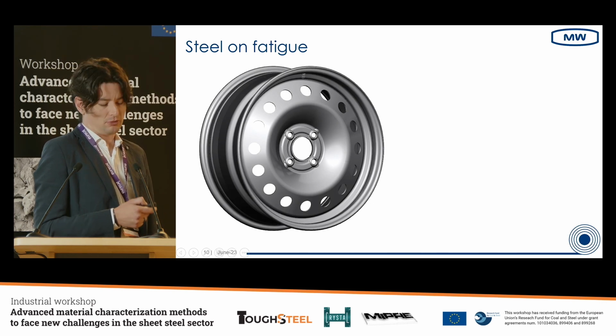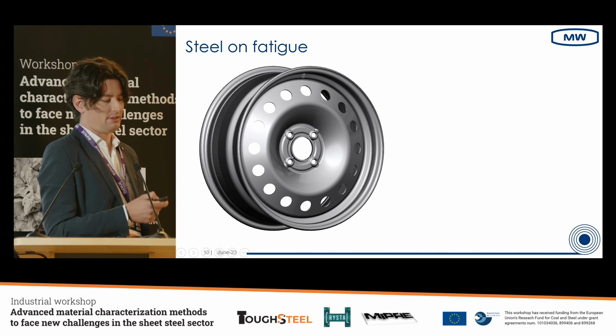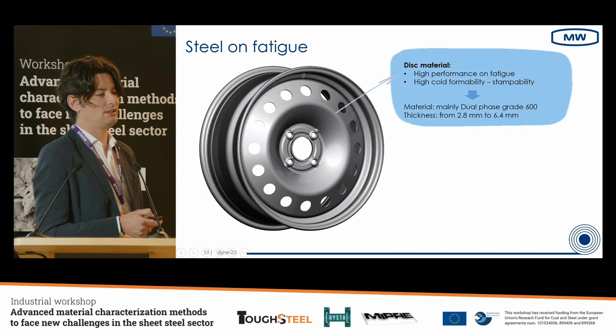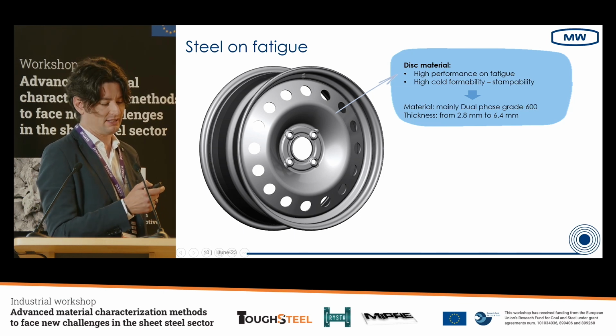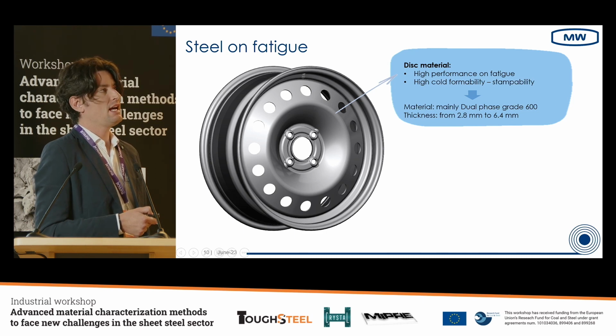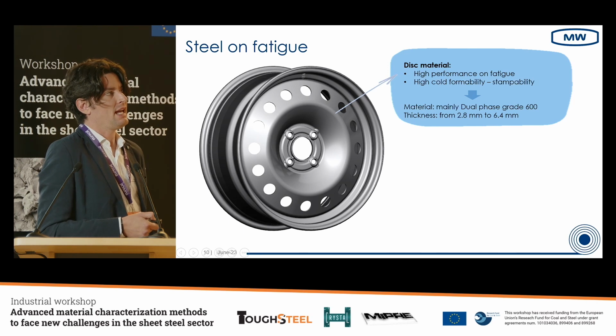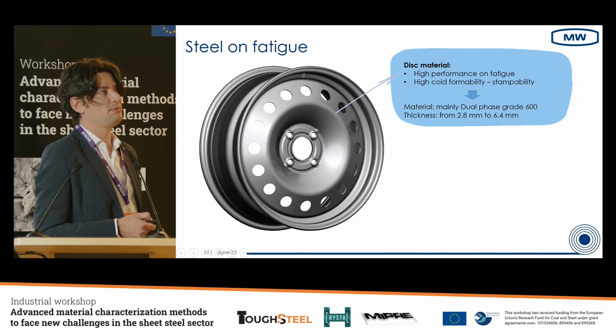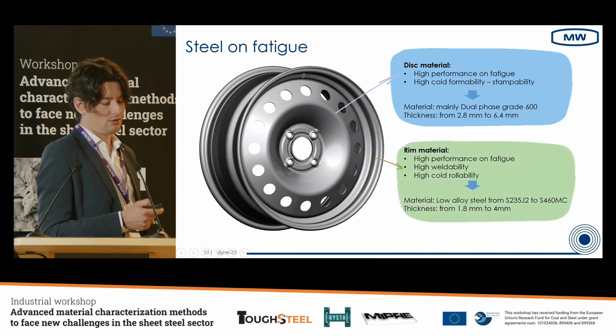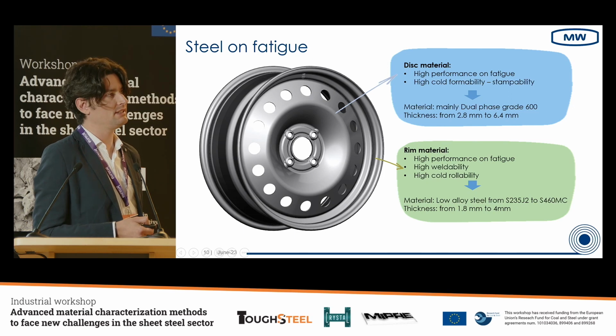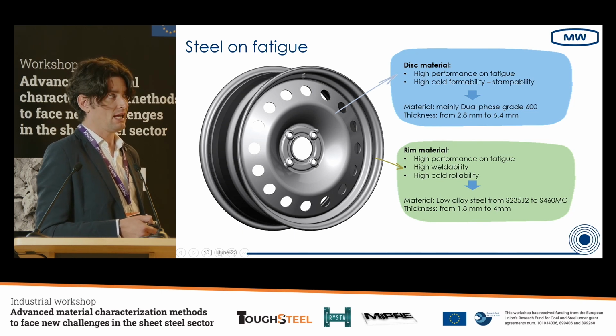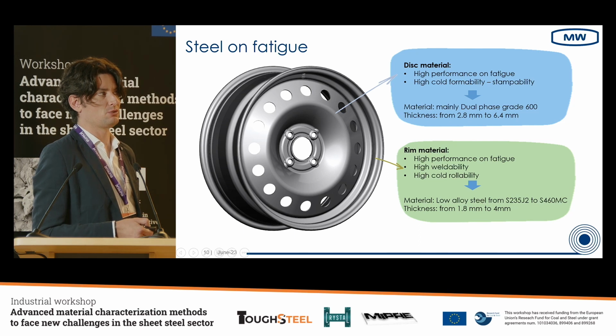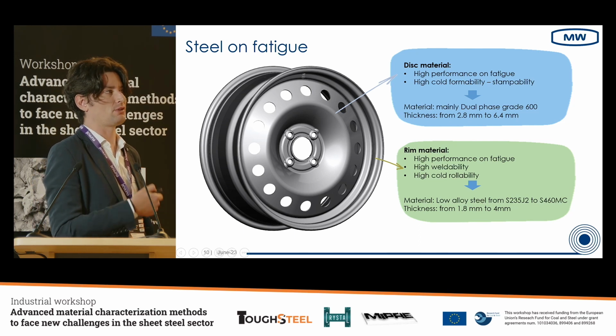So, for that reason, the wheel, which is composed of two different components, has different needs. For example, the material for the disc should have high performance on fatigue and high cold formability or stampability, and typically the material that we use for the disc is DP600 grade, with a thickness range between 2.8 and 6.4 millimeters. Regarding the rim, it should have high performance on fatigue, high weldability, and high cold rollability, and in this case the grades are low alloy steels from S235J2 to S460MC. And the thickness range is lower than the disc, between 1.8 and 4 millimeters. It depends on the load, the type of vehicle, and so on.